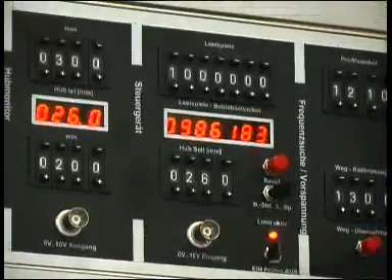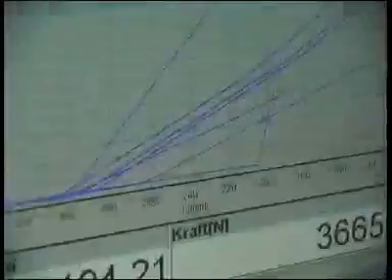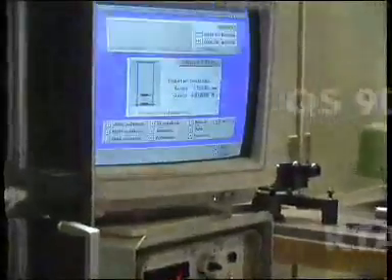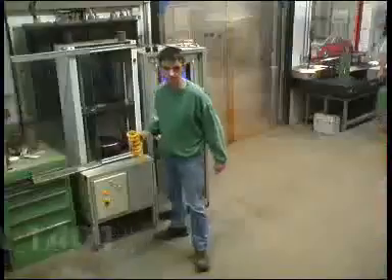At the end, there is the final inspection — a final check of the dimensions, the spring rate, and other specifications. In fatigue tests, suspension springs must, for example, withstand at least 500,000 times the full application of load and subsequent relief. Other products that we manufacture are even vibrated up to 3 million cycles, for example springs for fuel injection pumps. And this is a growing trend.